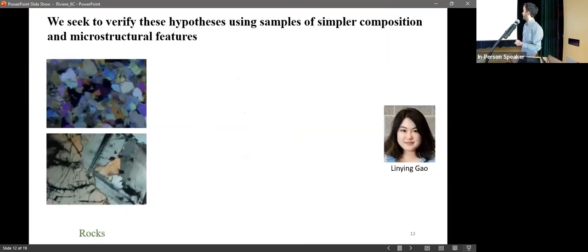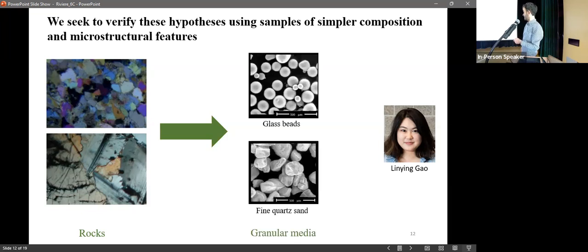Now my PhD student Linying has been working on doing these kinds of measurements, but with materials of simpler composition. Rock samples have large nonlinear elastic properties, or the nonlinearity is very high, but the composition is also very complex, so it's hard to understand the mechanisms. So she has been using glass beads, as well as sand samples. The grain size is about 100 micron, and so we know the composition. One of the differences is that for glass beads, the particles are very spherical. For sand, the particles are very angular.